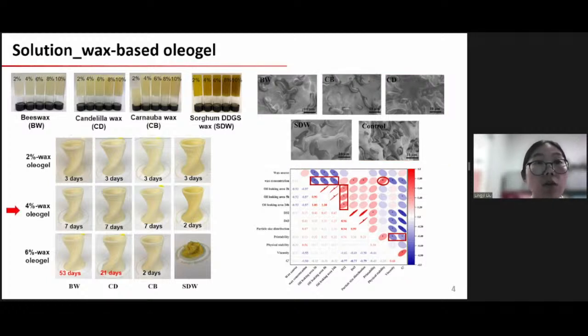If the wax oleogel was not formulated in the paste, the physical stability for the control sample was 2 days. But with the incorporation of wax oleogel, the days can be extended. We can see here the 6% beeswax oleogel can extend the days to 53 days. And 6% candelilla wax can extend the days to 21 days.